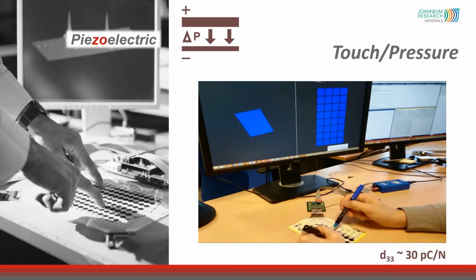The sensors are also piezoelectric, meaning that they react to pressure variations and to touch force, as shown here by the keypad activation. The piezoelectricity is parameterized by the piezoelectric coefficient, which is about 30 picocoulomb per Newton in our printed sensors.